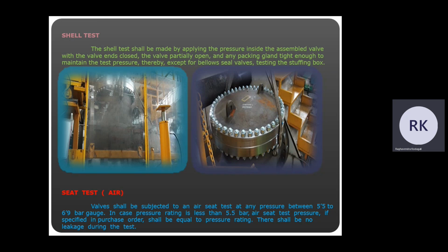Air test. The valve shall be subjected to an air test at any pressure between 5.5 to 6.9 bar gauge. In case the pressure rating is less than 5.5 bar, the air seat test pressure, if specified in the PO, shall be equal to the pressure rating. There shall be no leakage during the test.